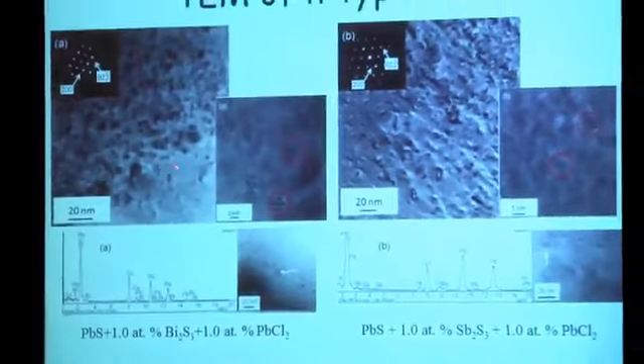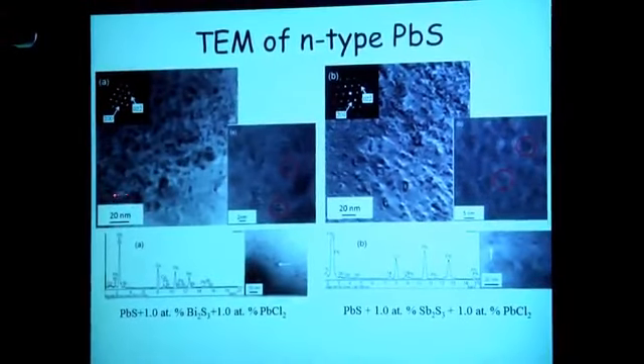Again, going into TEM, this is what you see. You see these coherent structures. It's nanostructured. It's not homogeneous. Here's the scale bar. So you have something between 2 and 20 nanometers, precipitated all over the place, bismuth sulfide.